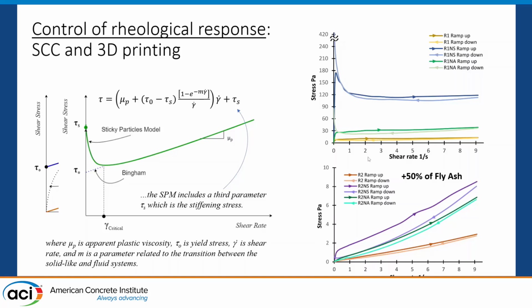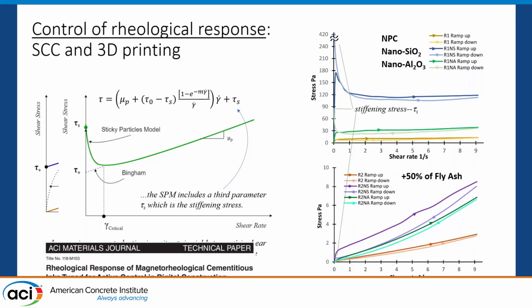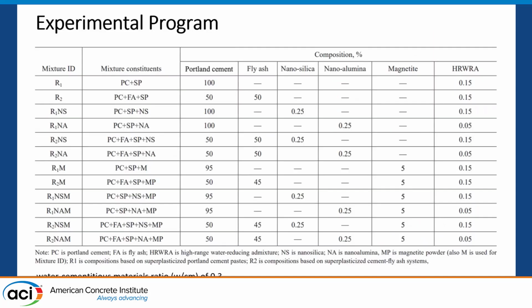cement system. So very small quantities of nanoparticles can change yield, but can also provide additional stiffening. This is what we observed. And again, nanosilica and nanoalumina are compared here. Well, results were published in ACI Materials Journal some time ago, and you can look at it more, but the